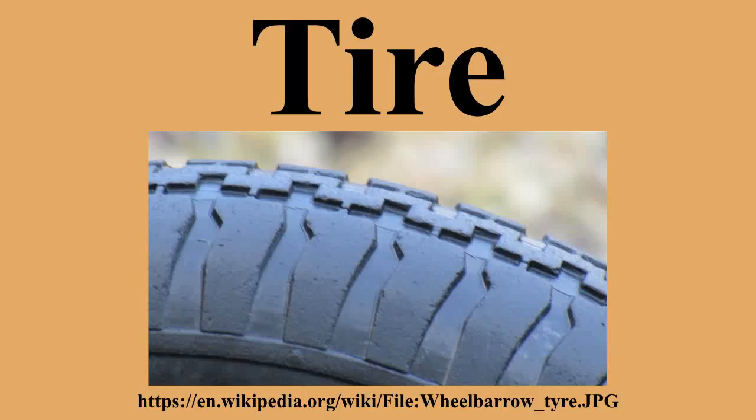The design was introduced by Armstrong, while Goodyear made it popular with the Polyglass trademark tire featuring a polyester carcass with belts of fiberglass. The belted tire starts with two main plies of polyester, rayon, or nylon calendered as in conventional tires, and then placed on top are circumferential belts at different angles that improve performance compared to non-belted bias tires. The belts may be fiberglass or steel. This technology was a temporary, not-invented-here stopgap, introduced by U.S. manufacturers to forestall the radial tire.